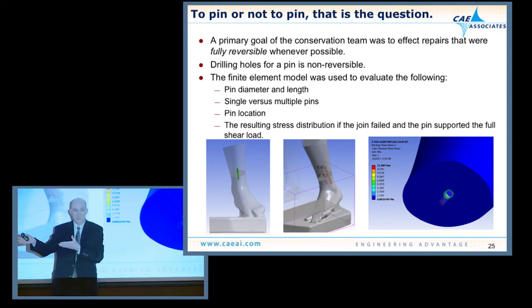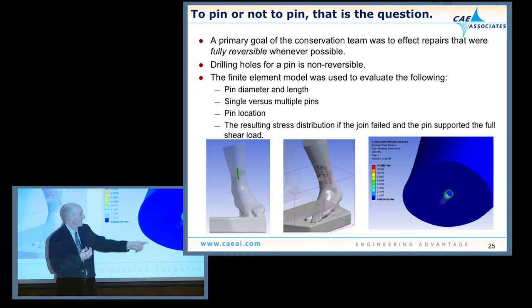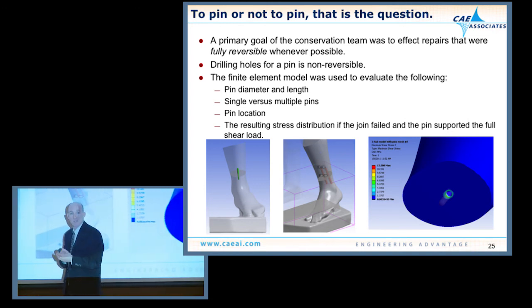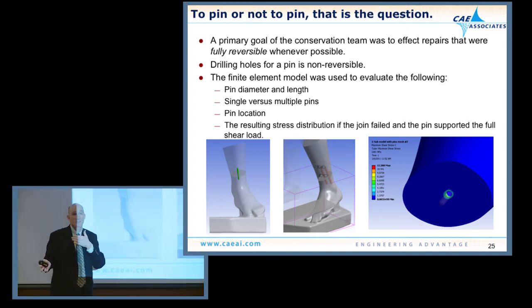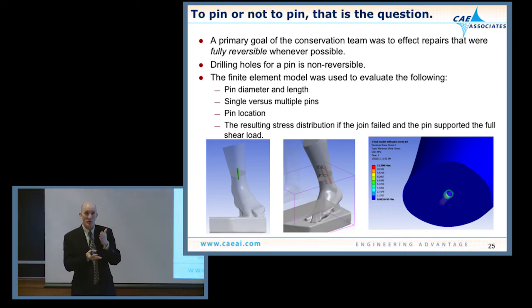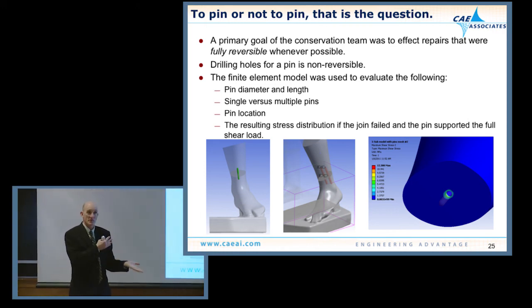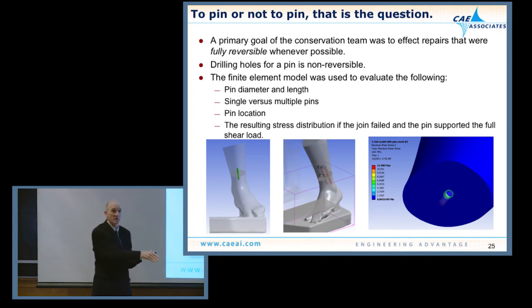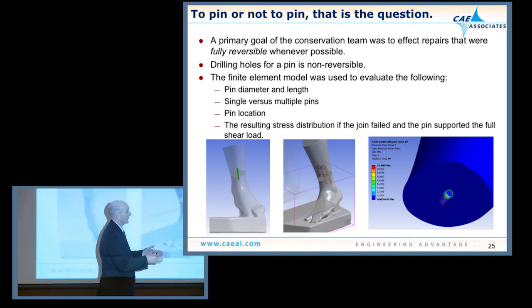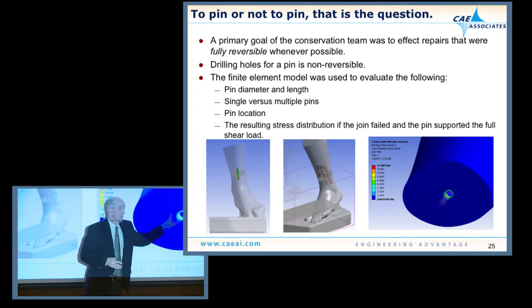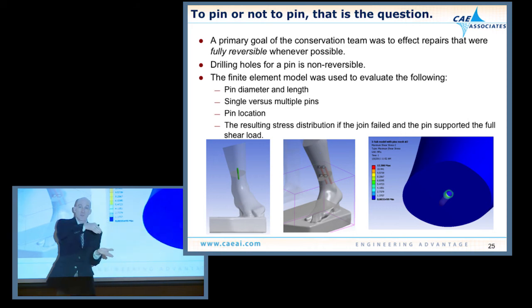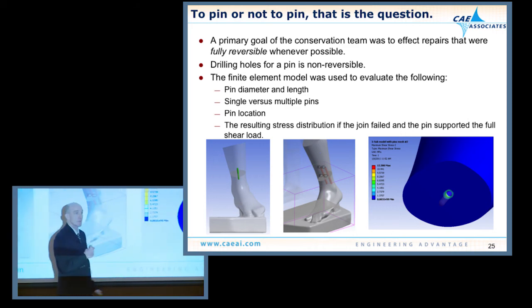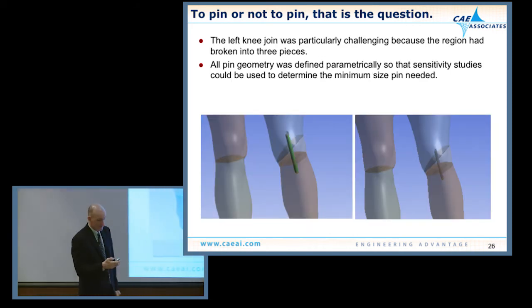One of the concerns they had in terms of the pin material choice was that they didn't damage the marble if the bond were to fail. Carolyn had mentioned the comparison of stainless steel pins, which caused the marble to crack locally, versus the fiberglass pin, which would shear first, not damaging the parent material. So we were able to also provide some information on the stress distribution if the bond were to fail and the pin were to take up the shear at the interface due to the statue's weight.